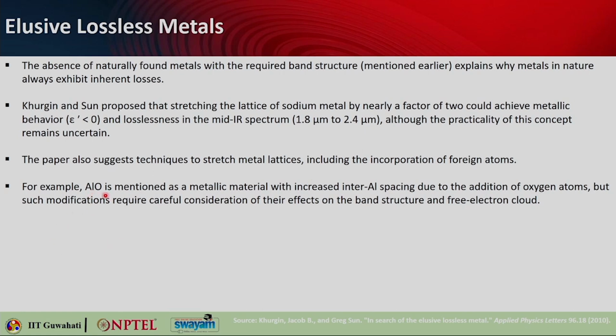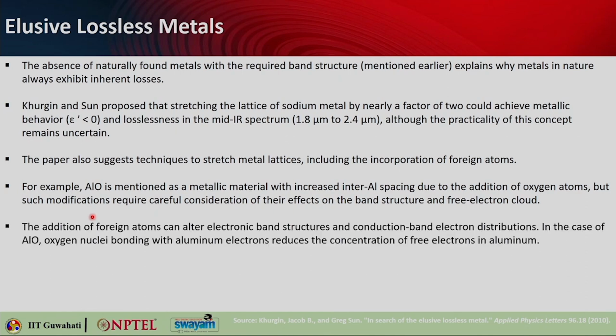For example, aluminum oxide is mentioned as a metallic material with increased inter-aluminum spacing due to the inclusion of oxygen atoms, but such modifications will require careful consideration of their effects on the band structure and also the free electron cloud. The addition of foreign atoms can alter the electronic band structures, that we all know, and also the conduction band electron distribution. So, in the case of aluminum oxide, oxygen nuclei bonding with aluminum electrons reduce the concentration of the free electrons in aluminum.